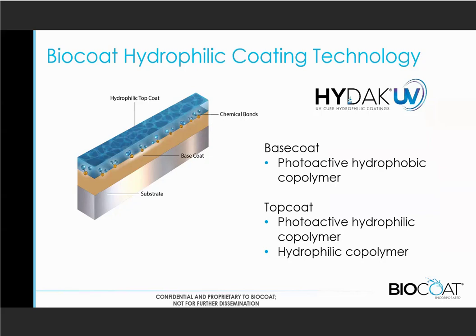The other part of it is, of course, the hydrophilic top coat, which is a combination of photoactive as well as just plain hydrophilic copolymers; we have a mixture of them. We dip coat them using standard techniques, apply it, and then when we hit that with UV light, again, it cross-links to itself, but also tenaciously bonds to that underlying substrate.